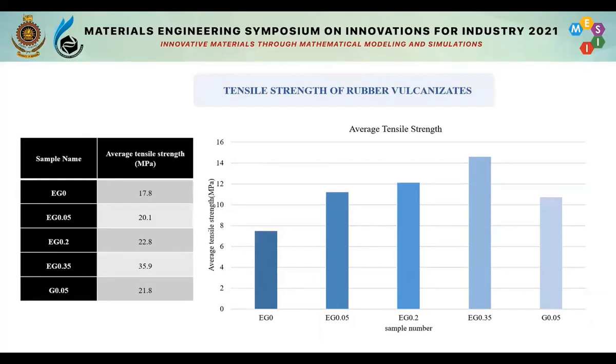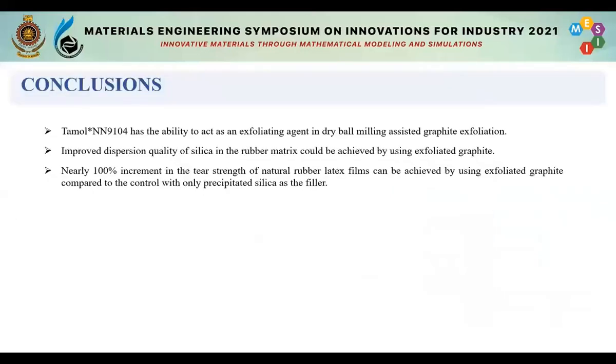And also, improved dispersion quality of silica in the rubber matrix can be achieved using exfoliated graphite. Nearly 100% increment in the tear strength of natural rubber latex films can be achieved by using exfoliated graphite compared to the control with only precipitated silica as the filler.